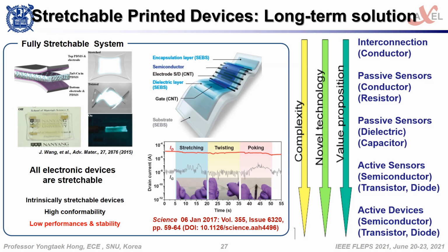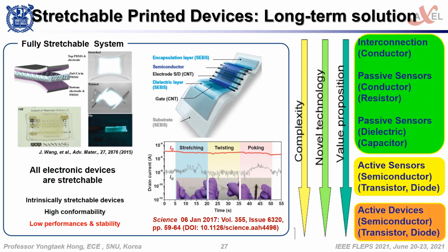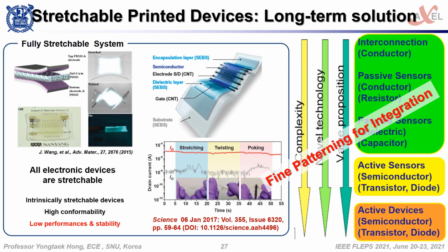In many cases, stretchable devices use ultra-thin structure or wire-shaped materials, so the device performances are typically poor, but stretchability is excellent. Depending on the type of devices, some of them are already printed on the stretchable substrate as shown in green color, and others are either under development or considered very challenging, as shown in yellow and orange colors respectively. In all cases, one big challenge would be fine feature patterning of materials for system integration.